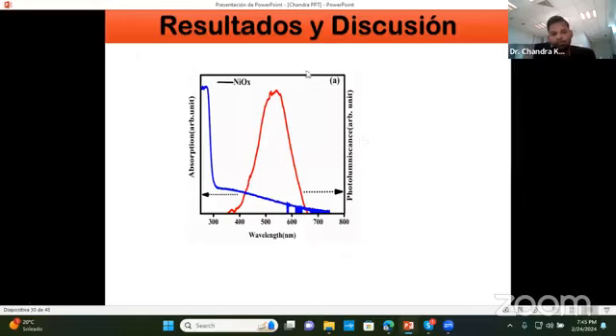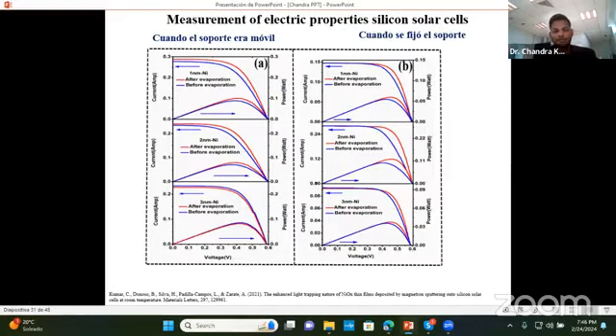See, in this way. This is the first and most important characteristic for down energy conversion: absorption should always lie in the ultraviolet range. However, emission might take place in the visible range. So first, we have to take the refractive index carefully. Second, we have to see the optical absorption edge, which here is around 320, 350 nanometer, and the emission comes around 530. So this is in the ultraviolet range and this is in the visible range. That fulfills the condition of down energy conversion, meaning a high energetic photon comes in, and through that luminescent material might be converted into different carriers or photons. So this is another possibility to enhance the short circuit current and obviously the potential and solar efficiency. So our result is explained through down energy conversion also.